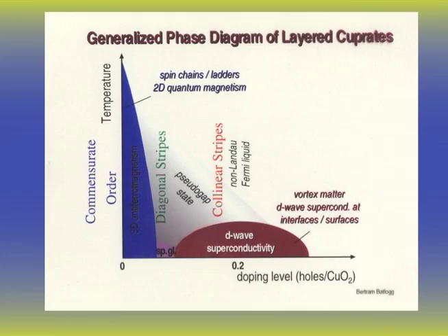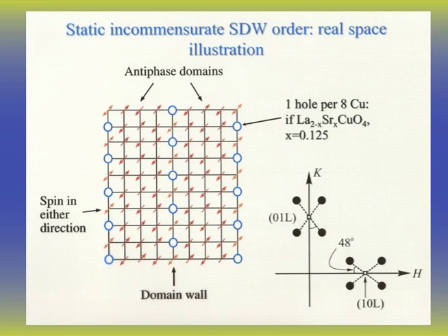After a lot of work, people then ended up systematically looking at the copper oxide materials and discovered a very elaborate phase diagram in which at zero doping, you have a magnetic insulator with a very high transition temperature. With only a few carriers, the bulk magnetism goes away. You enter into another peculiar magnetic state called a spin glass. And then at a magic concentration of 5.5% carriers, the material becomes a superconductor of D wave rather than conventional S wave symmetry. So this has led to an extraordinary amount of work, and I want to make this very brief, so I'm not going to dwell on it.